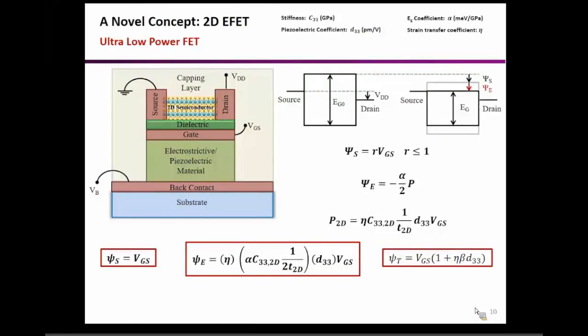So the strain you can get is, now if you do a back of the envelope calculation, generally the d33 coefficient for these electrostrictive materials, if you have a very good electrostrictive material and do some structural engineering, is 1 nanometer per volt. That's a typical number. So if you apply 1 volt to the gate, you can have 1 nanometer displacement. Okay. Now, if I also assume that my capping layer is perfect, nothing expands, then this 1 nanometer strain will be transferred into this 2D material.